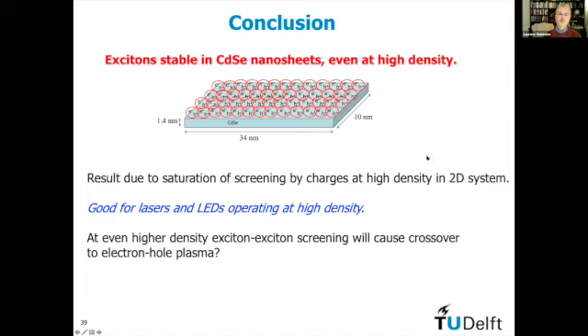So to conclude, we think that excitons are stable in cadmium selenide nanosheets, even at a high density where they start touching each other. And that is due to the saturation of the screening by charges at high density in a 2D system, surrounded by a low dielectric solvent. And that's good news for use of these nanosheets in lasers or LEDs that operate at a high density, because there you want stable excitons.